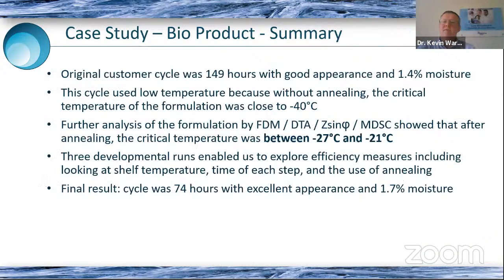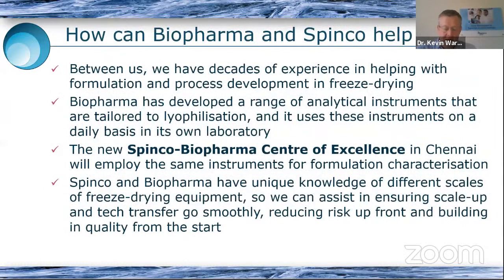So we halve the cycle time simply by doing more characterization, understanding the formulation better, establishing that we don't need to keep the formulation below -40 if we anneal it. We can go to much higher temperatures, and then we explored various efficiency measures, including looking at the shelf temperature at the time of each step, the use of annealing. We achieved a much shorter cycle time, but still with an average of 1.7% moisture. And again, as I said, this is the sort of thing we do all the time.